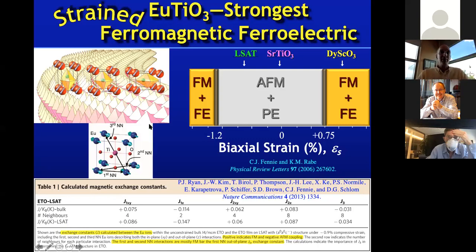So europium titanate, I mentioned how the europium is the only atom in europium titanate that has unpaired spins. It's got a half-filled f shell, so 7 Bohr magnetons on the europium. And the europiums have exchange interactions with nearest neighbor europiums, or second nearest neighbor europiums, or third nearest neighbor europiums, et cetera. And on the computer, Craig can calculate what the strength of those magnetic exchange constants are, those J's that describe the coupling, whether those couplings want to be ferromagnetic, whether the spins want to align, which would be a positive J, or whether they want to be antiferromagnetically aligned, which would be negative.